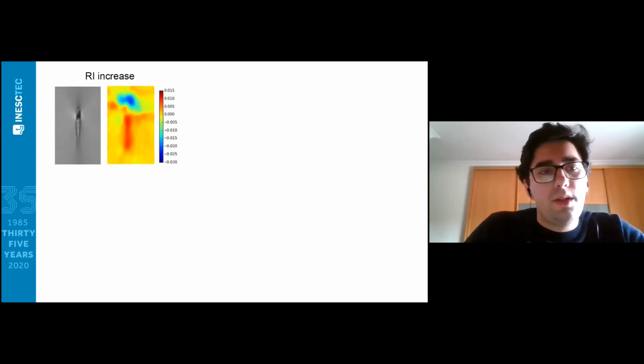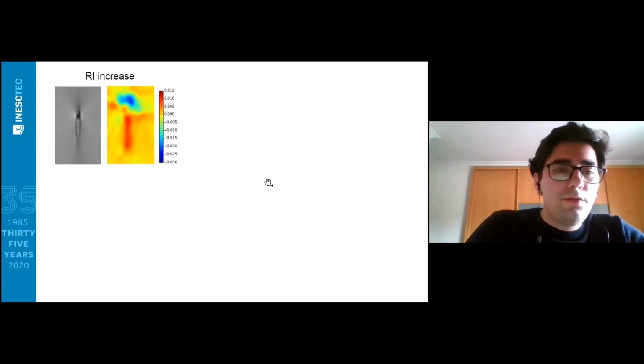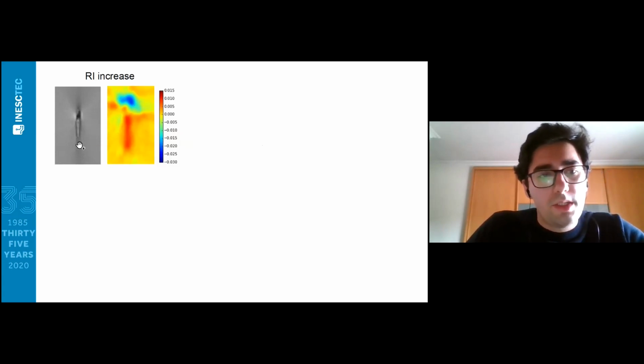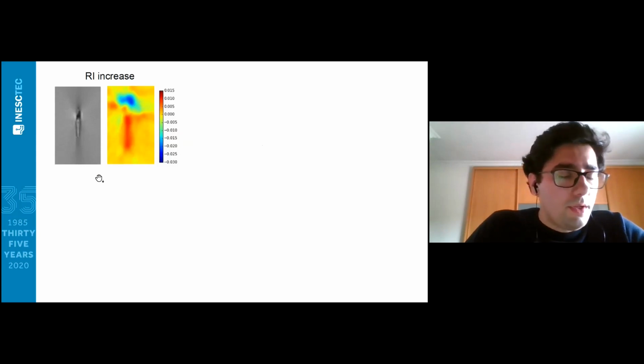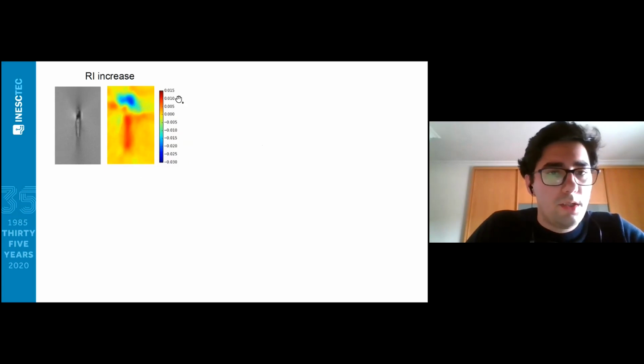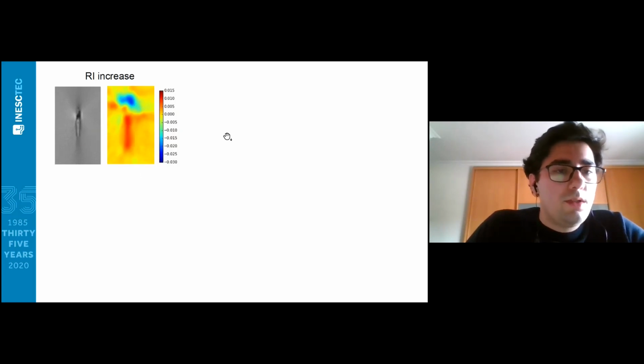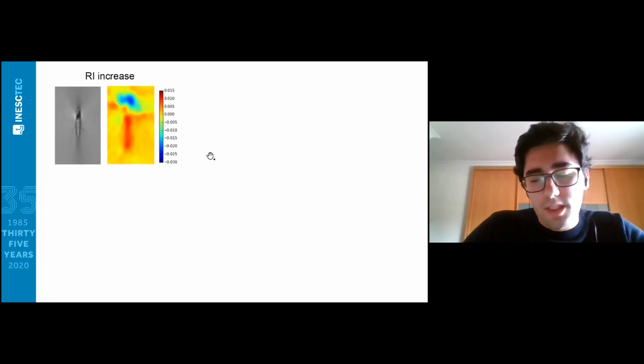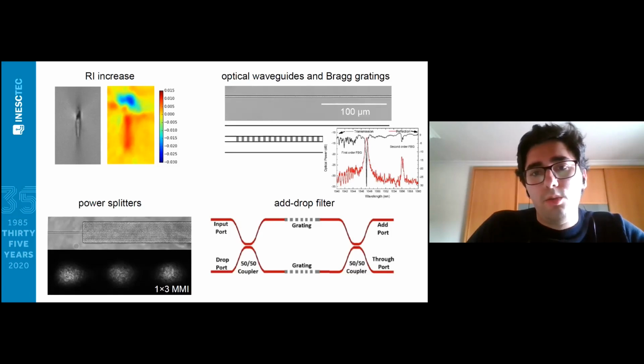As I said, the devices we can fabricate rely on the nature of the laser matter interaction. In fused silica, one of the possible modifications is an increase in the refractive index. Here, for instance, we have a cross-section picture of the laser modified volume, and this bright region is associated with an increase in the refractive index of around 0.01 or 0.015. This increase allows us to form integrated optics devices already, because just by having a localized index increase, light can be confined to this region due to total internal reflection. We have exploited this modification to fabricate optical waveguides, where light is guided through the irradiated path, as shown here. Light is only guided through this line.